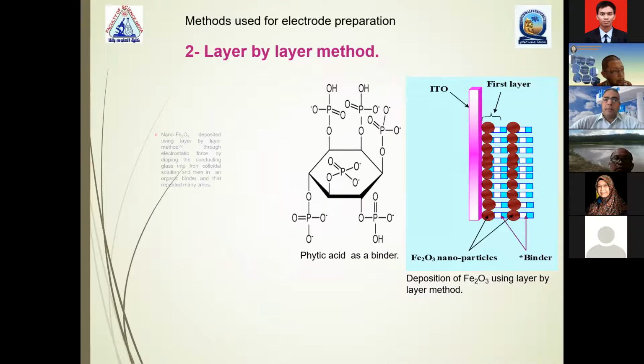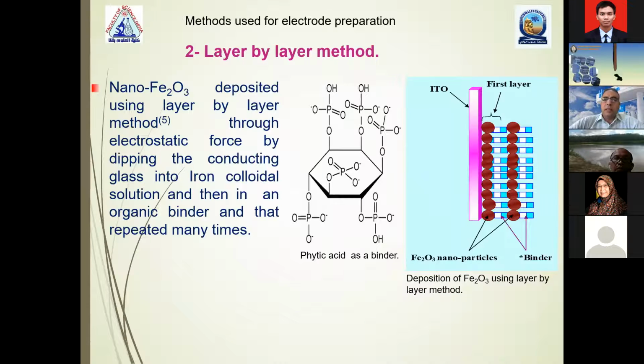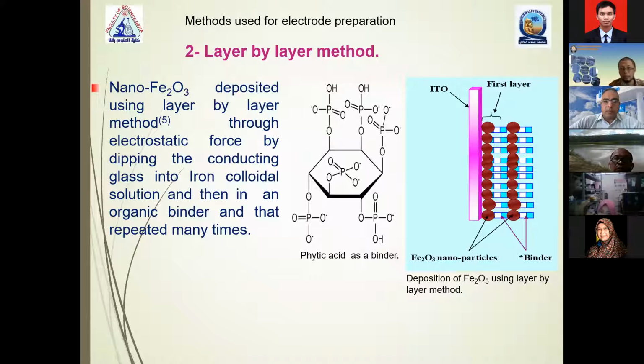Next. So we use another method which is called the layer by layer method, which is very simple as well, and can be done in any laboratory with very basic tools. We can use this electrostatic force to prepare a nanostructured iron oxide solar cell or solar electrode via deposition of layers of iron oxide, by dipping the conducting glass into an iron colloidal solution, and then into an organic binder like phytic acid, which is a binder. For example, this is ITO, or indium doped tin oxide, which is a conducting glass,